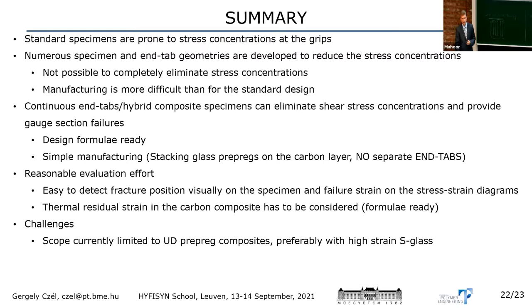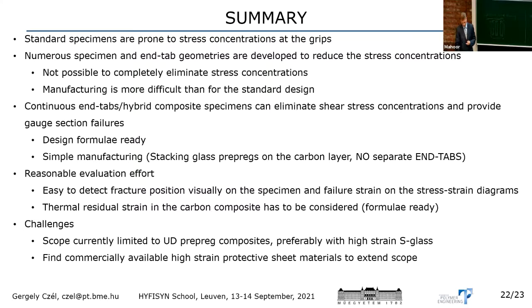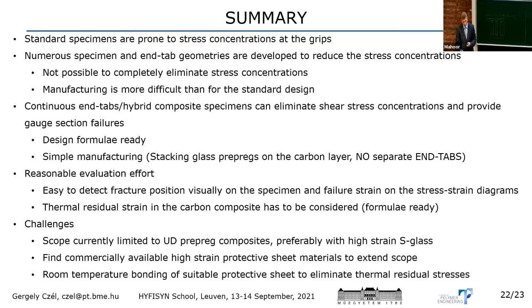Currently, the scope of this method is limited to prepreg-based composites with high strain S-glass as a protective layer. But we are looking at commercially available high strain protective sheet materials, maybe in a cured form, not in a pre-pregged form, which we can bond to laminates afterwards, and also to eliminate the thermal residual stresses. It would be excellent to come up with a good method to bond the protective sheet and the laminate at room temperature. So that would be one less